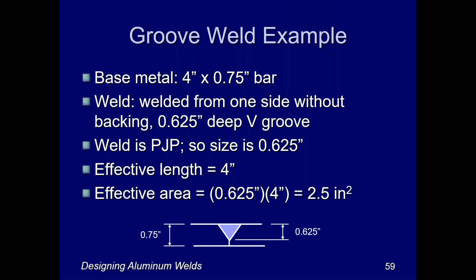And for the base metal, let's say that it's a 4 by 3/4 inch thick bar. And let's furthermore say that I'm going to weld it from one side without a backer, and I'm going to use a 5/8 inch deep V groove as my preparation. The reason we make that V groove, by the way, is to allow the welder access to the root of the joint so that he can get the penetration at the root. But if we don't use a backer or we don't back gouge and weld from the other side, we can't be assured of fusion beyond the root, and therefore that last 1/8 of an inch of thickness of the material here doesn't count as the size of our weld.